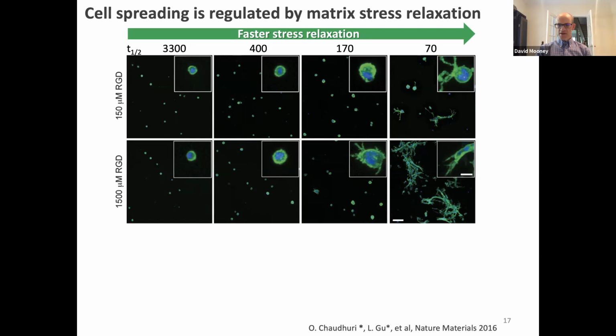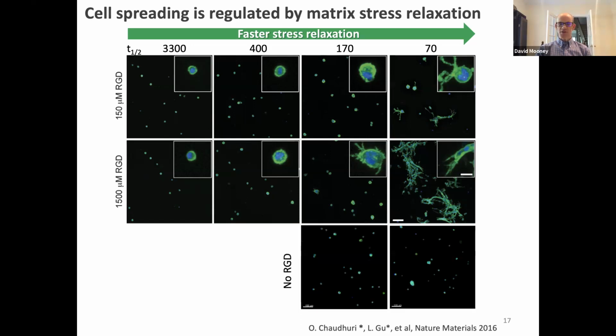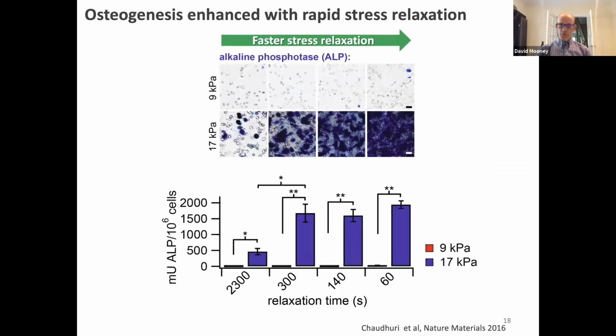Now, this was dependent on the ability of the cells to exert forces on the materials, because, for example, if we eliminated the ability of cells to pull and push on the materials by taking away the adhesion ligand, these effects were gone. So we could regulate a variety of fundamental aspects of the biology. We also found that the ability of these stem cells to become specialized tissue-forming cells was also regulated by the rate of relaxation in concert with the initial modulus.